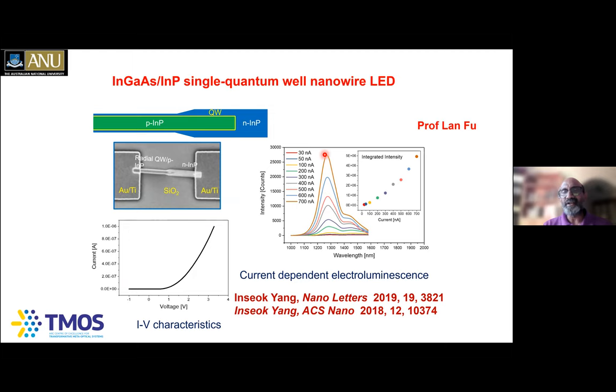One is here, one is here. That's mainly because the quantum well which has been grown on the top, the so-called axial quantum well, has a different thickness and composition of indium gallium arsenide with respect to this radial quantum well, which has a different thickness and composition there. So that's why you end up having two different emission wavelengths. But again, these are emitting in the near infrared region, which is the wavelength region important for optical fiber communications.